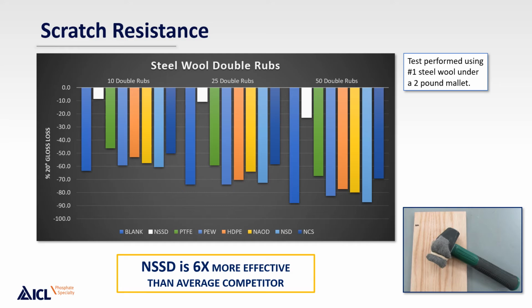So now let's review the scratch resistance for all of the additives combined. Again, just to refresh your memory, we used steel wool double rubs as our key property, and we measured that at 3 different levels of double rubs, just to provide a broader view of performance depending on what level of performance you're looking for in each lab. So 50 double rubs probably indicates the failure point for many formulations, depending on the resin system. In this case, you can pretty starkly see that the white bar of the NSSD provides a significant improvement versus any of the other additives. And this is a measurement of the change in gloss before and after each of these cycles.